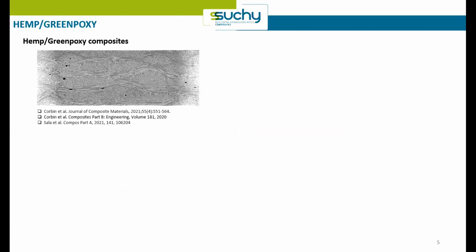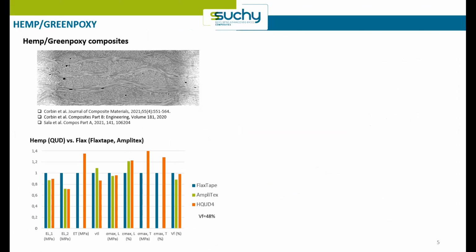In parallel, we also used the GreenPoxy system, the partially bio-based epoxy commercialized by Sicomin, with hemp reinforcement developed within the project. So we obtained very nice results. Most of them were already published, but here I propose a graph showing the performance at the scale of quasi-unidirectional